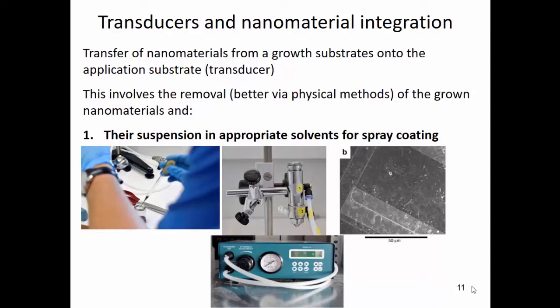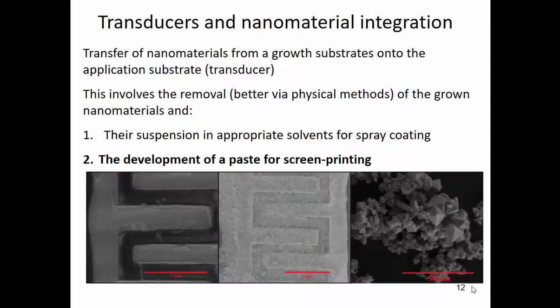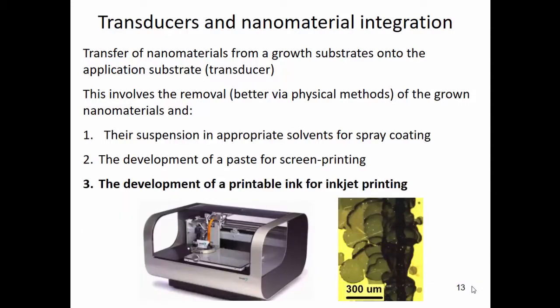Using an airbrusher spray coating system, we achieve very thin films — you can see the electrodes sitting below through the film. With screen printing using stenciled electrodes, we coated a film of indium oxide octahedra obtained from oxidation of an indium chloride precursor. More recently we are starting to develop printable inks and using an inkjet printer to achieve a fully printed sensor — inkjet printing both the transducer and the nanomaterials on top.